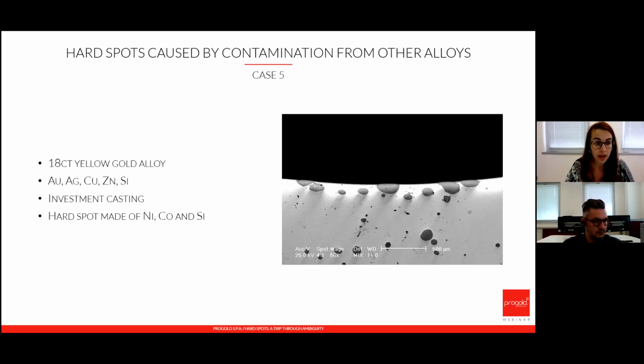In this case, we have a 18ct yellow gold alloy, and the person that was using it was mixing it with other pieces that had similar composition, but the other alloy had cobalt in it, which is a grain refiner. And the cobalt decided to react with nickel and silicon instead of just remaining as a grain refiner, due to a series of thermodynamical considerations.